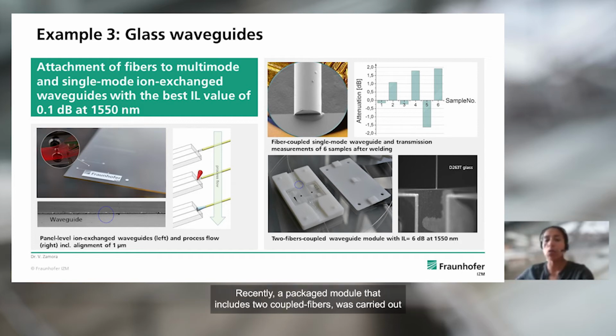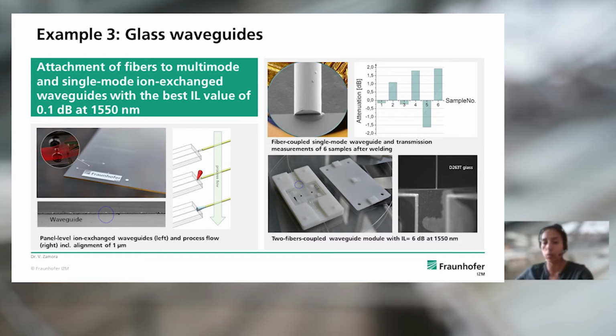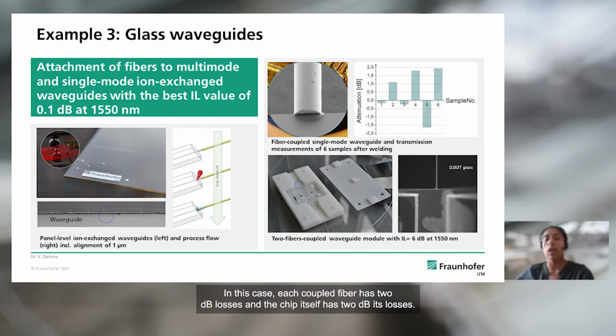Recently, a packaged module that includes 2 coupled fibers was carried out, where a total insertion loss value of 6 decibels was measured. In this case, each coupled fiber has 2 decibels losses and the chip itself had 2 decibels losses. Although the construction of this model is still under optimization, we see potential in applying the laser welding process to optical waveguides.